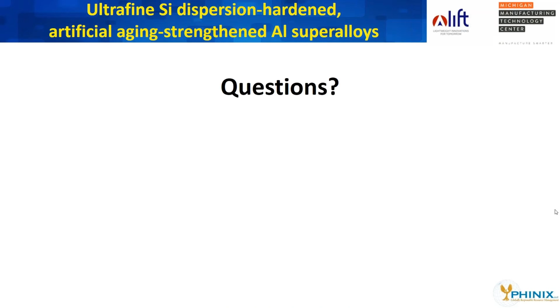And what was the thickness of the casting? The sample was 20 millimeter diameter, 30 centimeter long. And so this is a laboratory size sample made in the casting simulator. And what we are aiming at now, and we already have dies designed to cast dog bone type tensile test samples, is trying to match the process conditions that we achieved in the casting simulator in real high pressure die casting dies under industrial conditions.